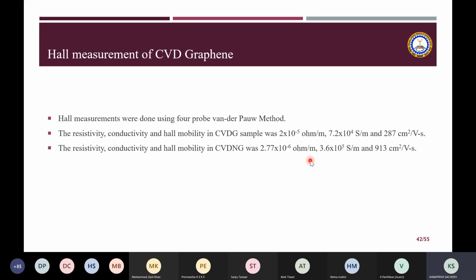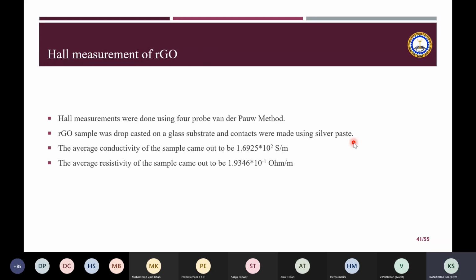Now, when we did the Hall measurements on the CVD graphene, that means the graphene which we grew using CVD, we found the conductivity to be of the order of 10 to the power 4 Siemens per meter, as compared to 10 to the power 2 Siemens per meter. So there is an increase of 2 orders of magnitude in conductivity in CVD graphene as compared to the RGO sample.